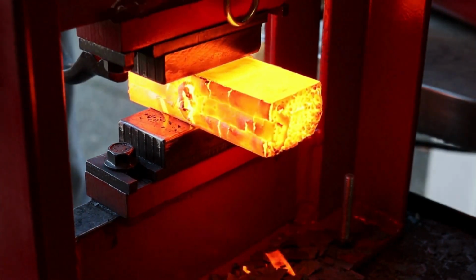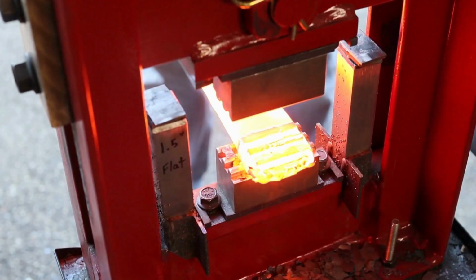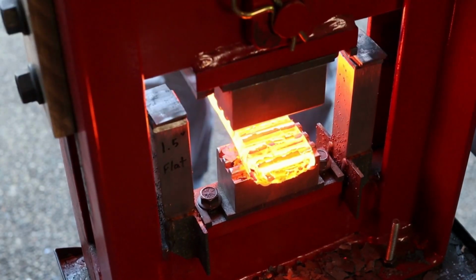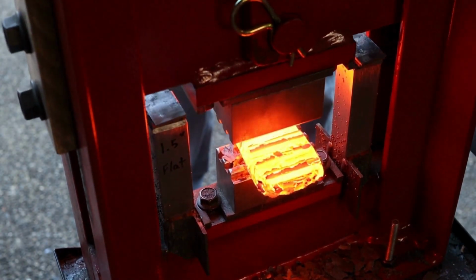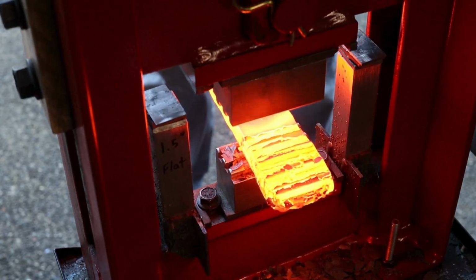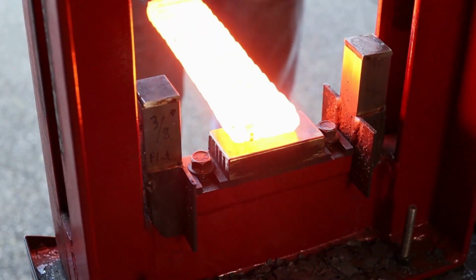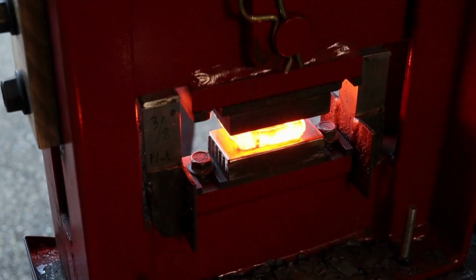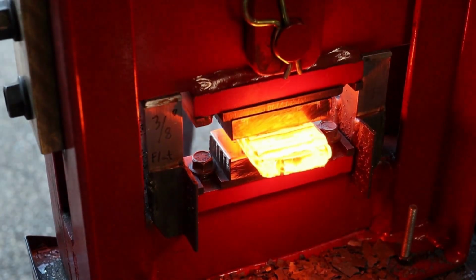Since this is my last stack for the billet, I'm going to press in a pattern with some ladder dies. With traditional ladder Damascus, you'd then grind off the ridges to get a flat billet, and that would give you a very bold tiger striping effect to your billet. In this case, I'm just going to press the billet flat, and it gives a more subtle wave-like pattern.